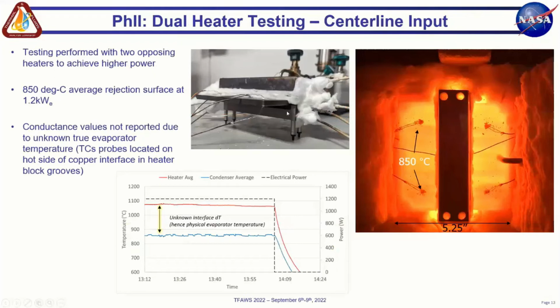So to do so, we needed a second heater block bolted up opposing the original one in this sort of clamshell sandwich construction. So we were burning up lots of those Incoloy cartridge heaters. And now with 2 cartridge heaters, we're able to run higher powers. So at 1.2 kilowatts electrical in this configuration, we're able to drive the condenser surfaces up to 850C. And we internally like this picture on the right a lot, generated a lot of excitement internally at Thermovant to see the ability to make these really hot OHPs that are showing good performance.